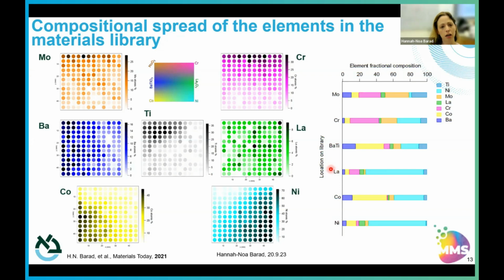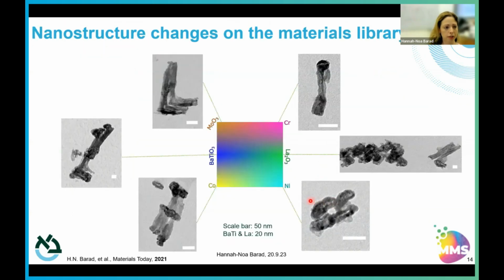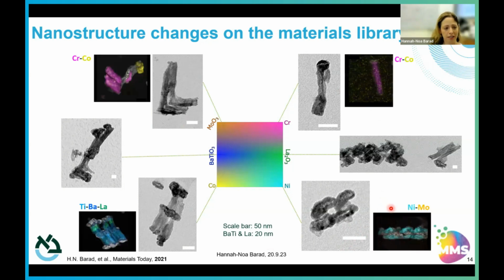So now that we have compositional gradients, we asked ourselves, do we actually form different types of nanostructures in this single one-shot deposition process? And indeed, we really do. So we go from L-shaped nanostructures on the molybdenum side through some intermediate down to, we like to call these bone-like structures, but anyone can imagine whatever they want, on the cobalt side. And then match-like structures on chromium through two types of intermediates down to these zigzags on the nickel side. And each of these nanostructures also has its own different type of composition.